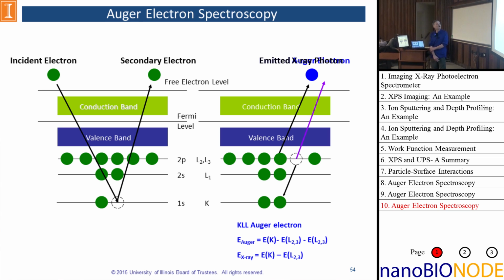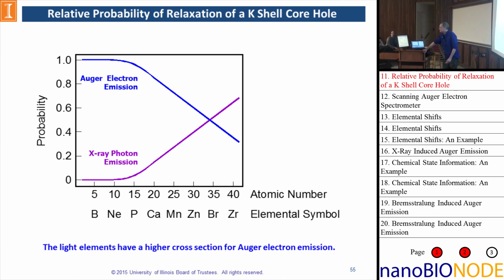Here is once again a repeat of the physics. The electron comes in and excites a secondary electron, and then through a relaxation process, an upper shell electron falls to fill that hole, and the third electron, the Auger electron, is emitted. This is what we'll be looking at. Just a reminder that the complementary process is the emission of an X-ray photon. And the probability for, in this case, a K-shell relaxation resulting in an Auger electron is much higher for the lighter elements than the heavier elements.